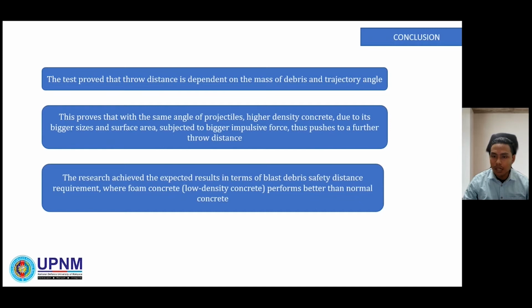Assuming low trajectory, as illustrated in the figure before, bigger size debris from normal concrete, which is the higher density, exhibits bigger composition at far range. This proved that with the same angle of projectiles, higher density concrete, due to its bigger size and surface area, is subjected to bigger impulsive force, thus pushed to a further throw distance.